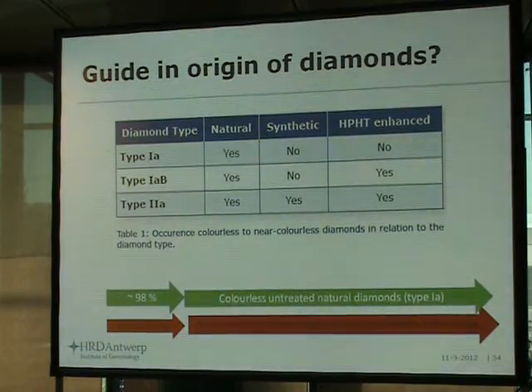Most important for you, when you're dealing with colorless and near colorless diamonds, say the color range D to K or tinted color range, is that when you get the result from infrared or from the analyzer and you get a type 1A result for colorless near colorless, then in statistical terms, roughly 98 or 99%, depending on your statistics of course, these are colorless, untreated diamonds with respect to high pressure, high temperature treatment. These diamonds are not found synthetically and cannot be high pressure, high temperature enhanced, because if you would, for example, apply high pressure, high temperature treatment, then you would achieve yellow-green diamonds. We are talking about colorless to near colorless diamonds.